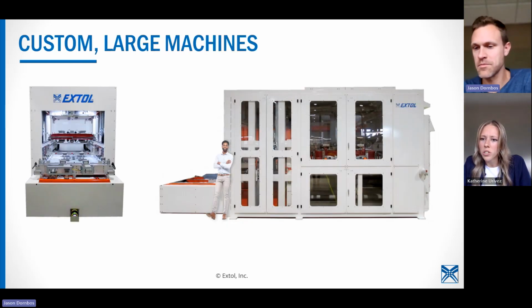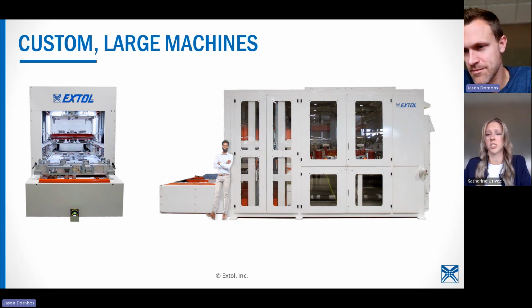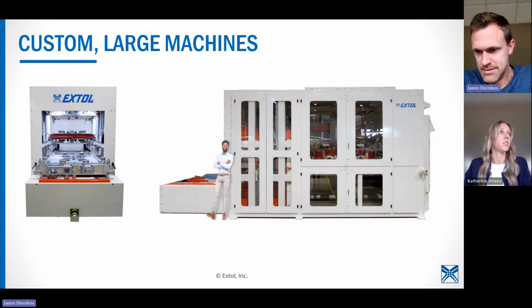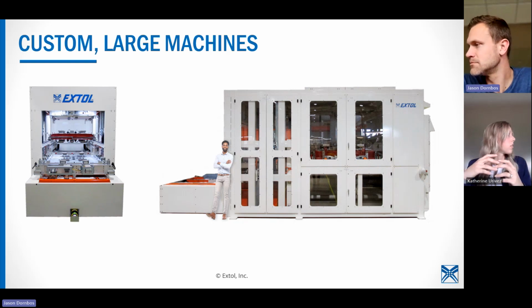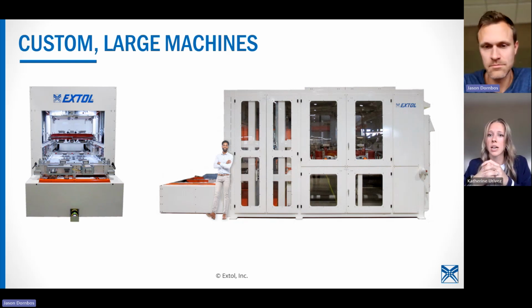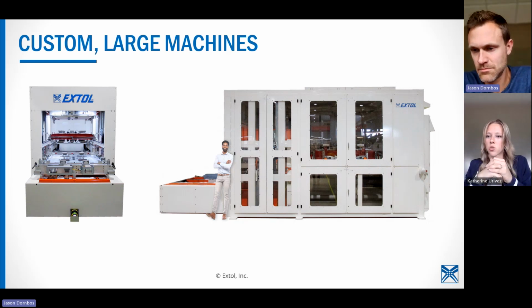We've got some questions about what coating is best for polypro copolymers. We've welded copolymers with both chromium and Teflon. So really it came down to part geometry and how the part was stressed under like the burst test or leak test and needing to get maybe a little bit of strength out of it. So we have definitely tried both, depends on the application.